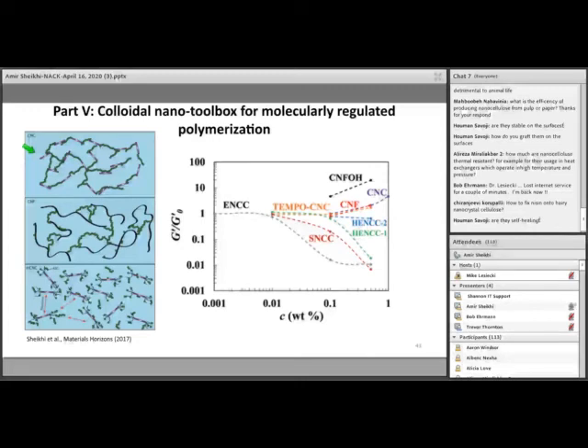Typically, conventional nanocelluloses are used for increasing the viscoelastic properties, or the storage and loss moduli, of materials such as hydrogels in the form of nanocomposites. And as you see here, cellulose nanocrystals and cellulose nanofibrils increase the storage modulus of a model gel as the concentration of these nanoparticles in the gel network increases. But what we observe with hairy nanoparticles is that they not only don't increase the storage modulus,